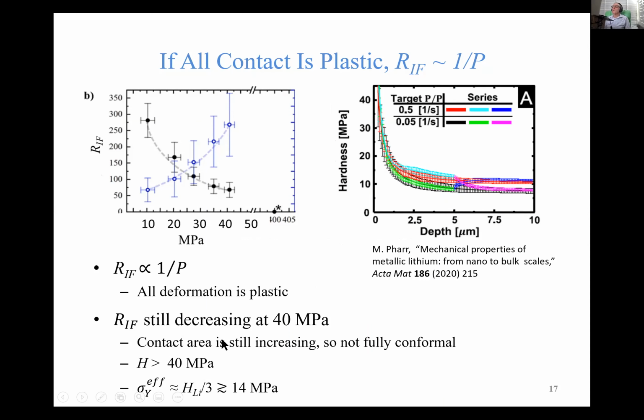Now, if you're uncomfortable with the idea that the hardness of lithium can be 40 megapascals, here's some data from M. Pharr. It's nanoindentation data, where he's measuring the hardness as a function of the size of the indentation. And what we see here is a very large size effect. Size effect is sort of universal. This is a pretty steep one. Down where the indentation is at the submicron level, you get a 40 megapascal hardness.